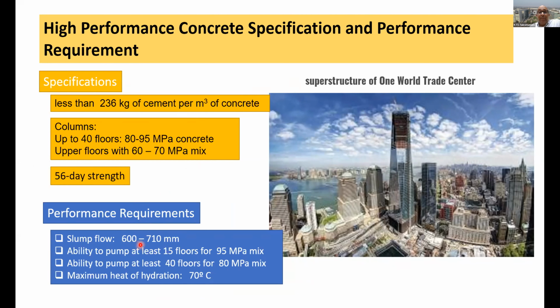The concrete had to have a flow, not slump. It is slump flow of 600 to 710 mm. That means it literally spreads itself very easily under its own weight. It should have the ability to pump at least 15 floors for the 95 megapascal mix. And the concrete, which is 80 megapascal mix, should be pumpable to 40 floors. And the maximum heat that is produced in the concrete during hydration should not exceed 70 degrees Celsius.